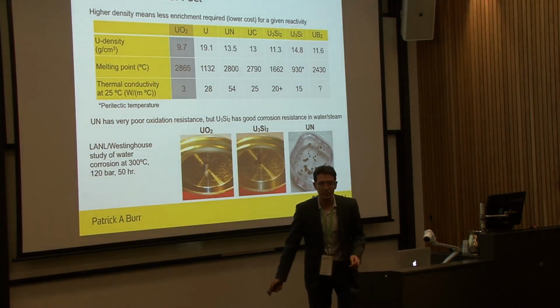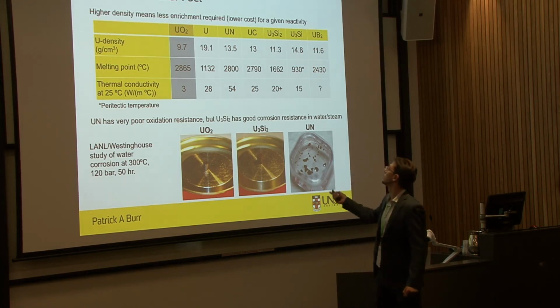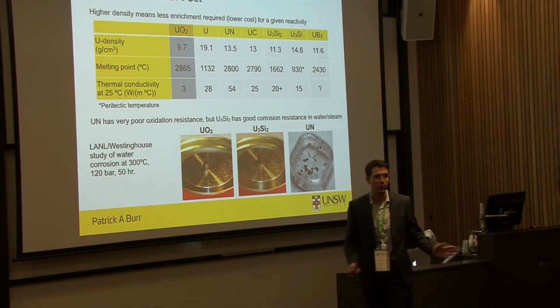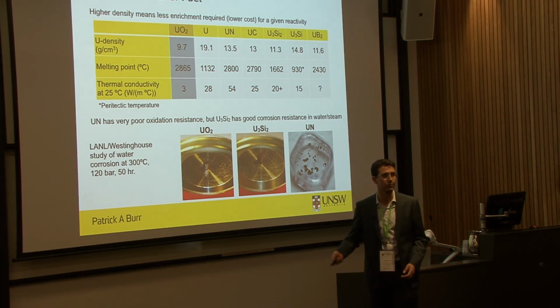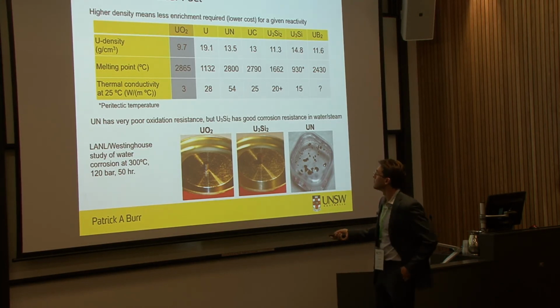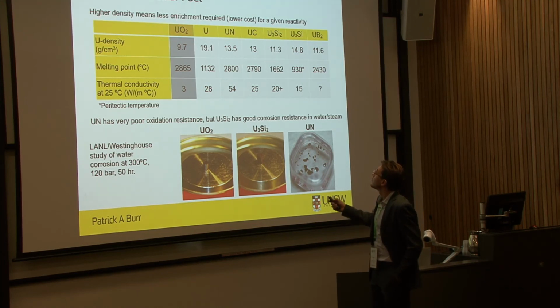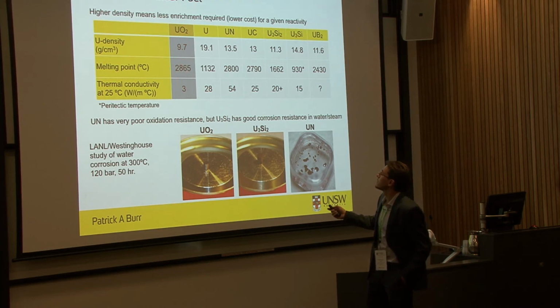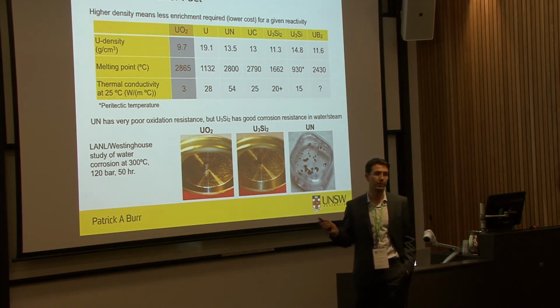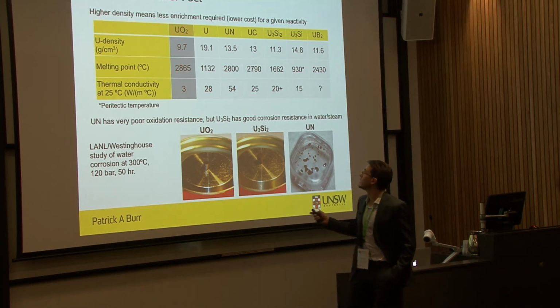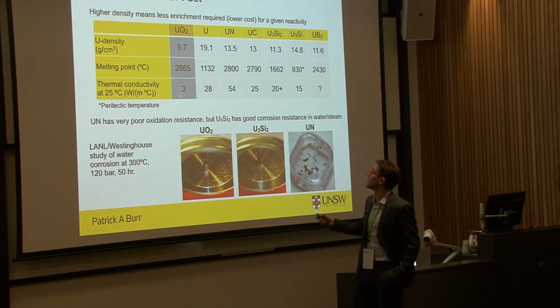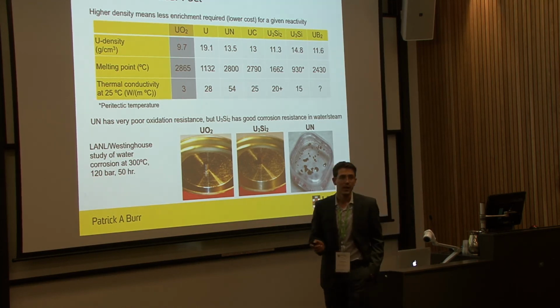So, just comparing some basic properties of some uranium compounds, and this is only looking at uranium. Of course, one could look at thorium, plutonium, and other potential fissile material. Comparing them with uranium oxide, you can see that, first of all, the melting point of uranium oxide is incredibly high, and we're probably not going to beat that. But the thermal conductivity of uranium oxide is absolutely dreadful.